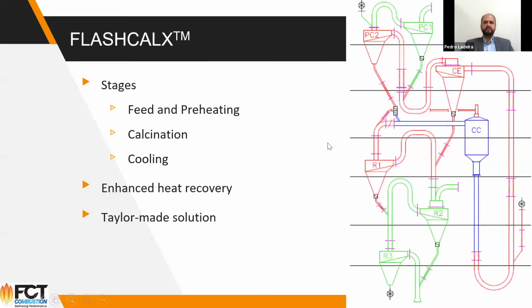On the flash calcination, the other way, it's quite comparable to a conventional pre-calcining kiln, preheater tower, where we have preheat stages, we have a combustion chamber, we have a calcining path, and then you have a cooling process. It has different possibilities, but we know we can enhance the heat recovery, and we can have a tailor-made solution for each case.